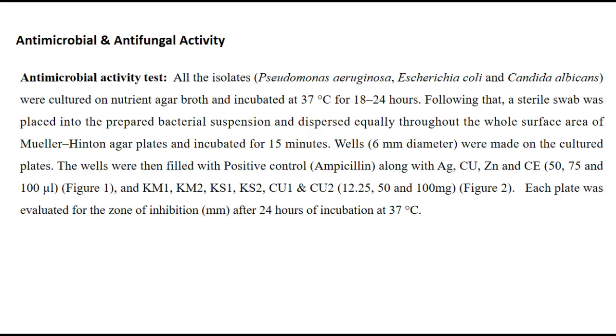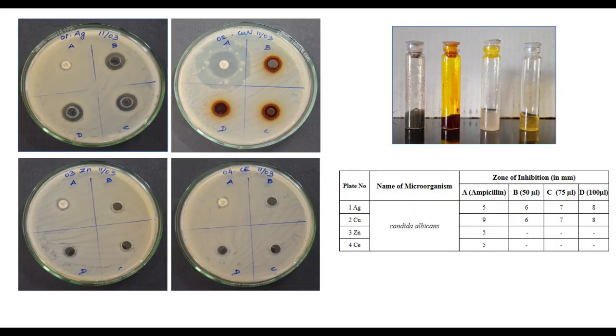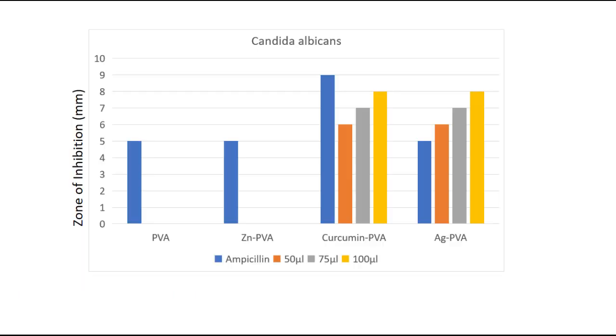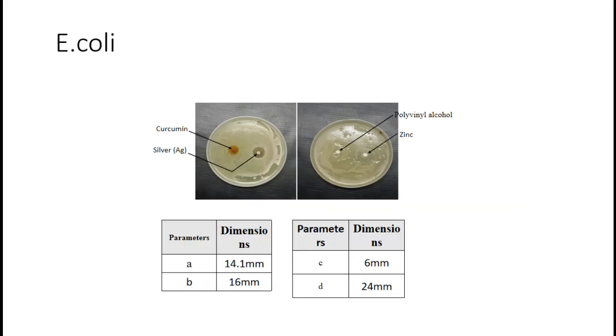In antimicrobial testing, the biofilm forming bacteria and fungi were taken for the zone of inhibition test. As we see in the first, antifungal testing, 4 samples were taken. One is polyvinyl alcohol alone, and another 3 are polyvinyl alcohol with silver, curcumin and zinc. For fungal activity, we took Candida albicans. In that test, it shows that curcumin and Ag show higher antifungal characteristics than zinc and normal polyvinyl alcohol.